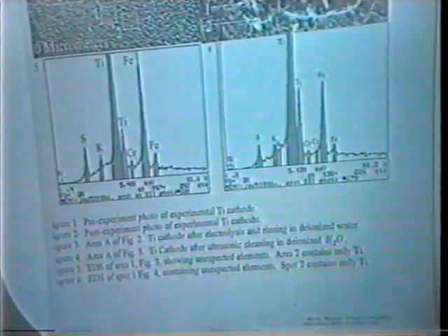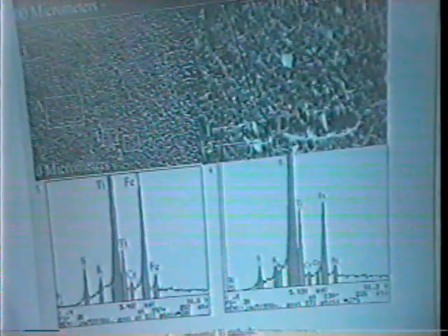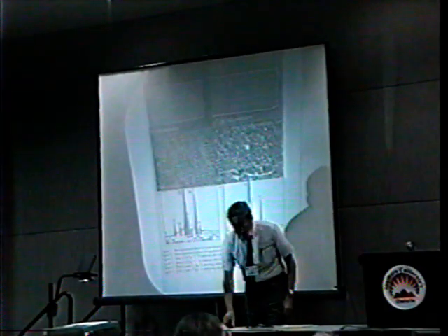Okay, then we did ultrasonic cleaning, and now this area A is magnified over here, and we have analyses from points 1 and 2, and again we confirm these elements, and the other area gives only titanium. Now at still higher magnification, maybe you can see things a little better.